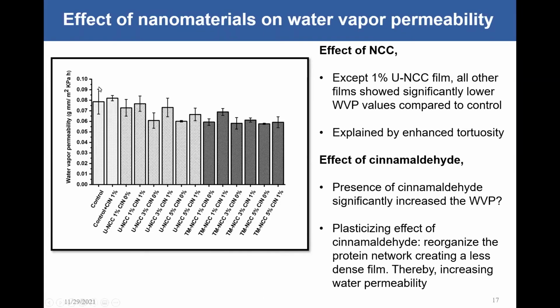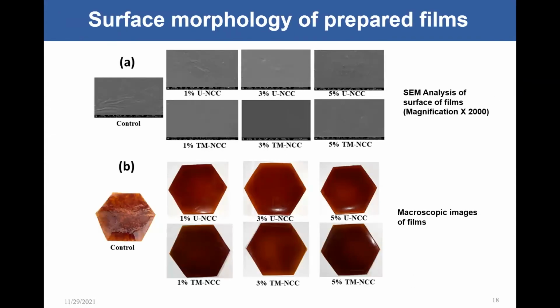Water vapor permeability, compared to the control sample, shows a slight reduction, but not too much with the TEMPO modification. So that's why we did another modification at a later stage to improve the water vapor permeability as well. This is how the packaging films would look at different nanomaterial addition levels, as well as the scanning electron microscope showing the surface roughness, especially at TEMPO modified nanomaterials.